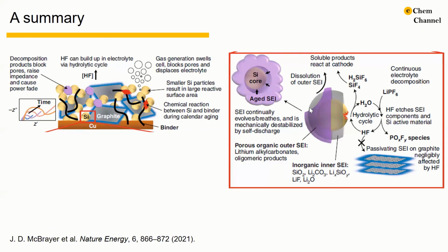Here is a schematic presenting the mechanism of long-term performance fade in silicon-containing anode due to silicon and SEI reactivity. Several processes occur when the cell is aging, for example, gas generation, irreversible reaction between silicon and binder, impedance rising, and the decomposition and dissolution of the SEI layer. The SEI layer formed on the silicon undergoes continuous change due to SEI reactivity with HF. This persistent electrolyte reactivity experienced by silicon and its SEI can accelerate capacity fade while also generating solid deposits that can block pores in the anode.